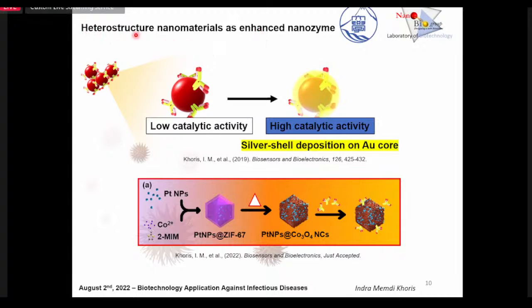So what is a heterostructure? It means a nanomaterial with two kinds of components, which we call a heterostructure or heterocomposite. The first one, published in BNB 2019, combines gold nanoparticles and silver nanoparticles as a coating on the surface of the gold. After the conjugation, we call it silver shell deposition on gold core, which shows a high catalytic activity.